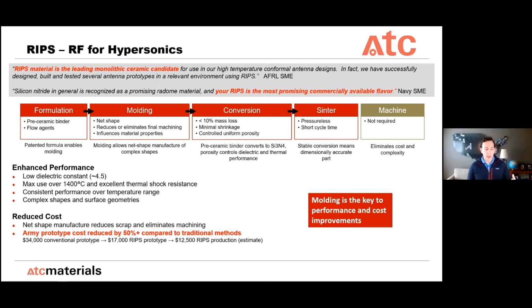And then the key part then is what we would then call conversion. So burnout might be a traditional term, but we have very little mass loss because of the formulation that we use. And this means that the part doesn't shrink much during this process. And it means that it is very dimensionally stable during this process. So that's what allows us to mold a green part and then carry it through conversion and sintering and maintain the shape. And this is also where that controlled uniform porosity is going to be created.